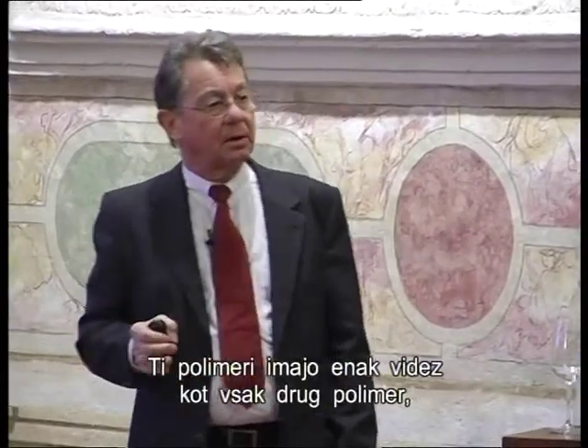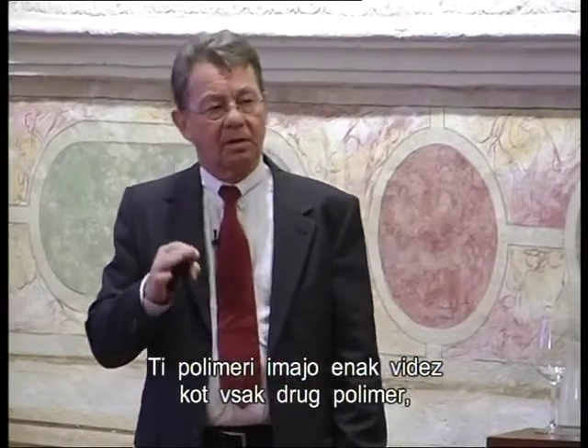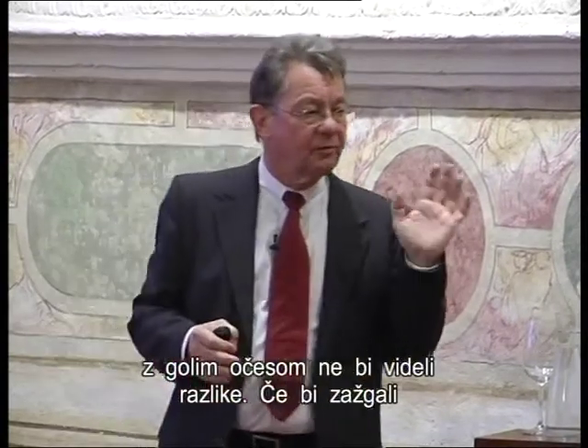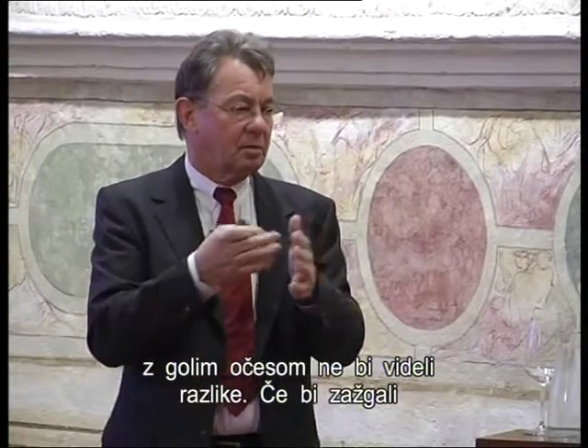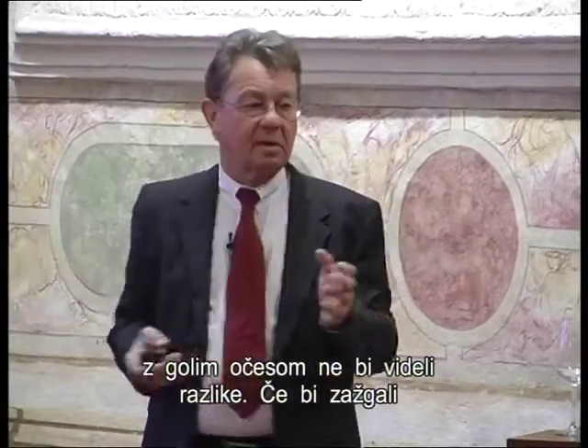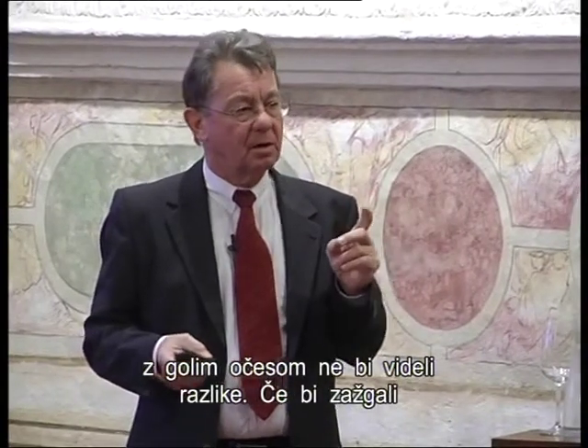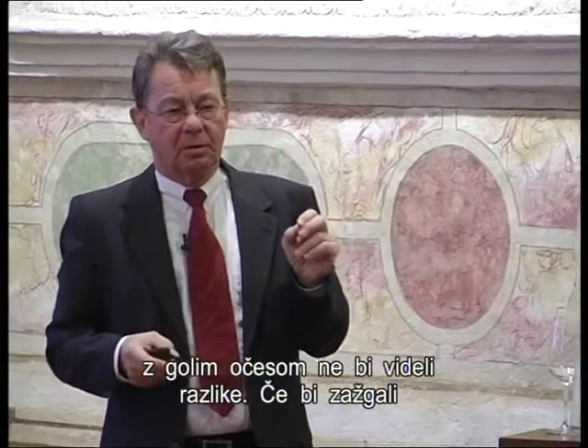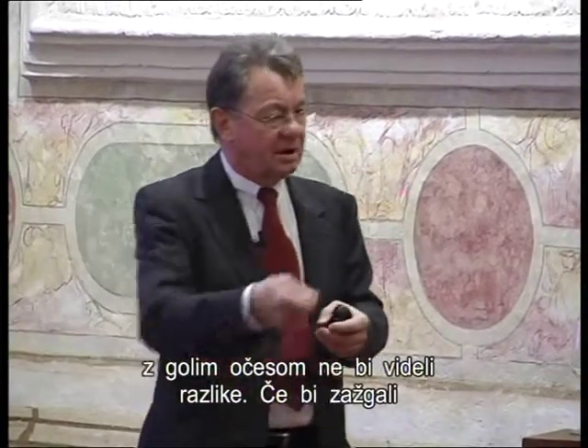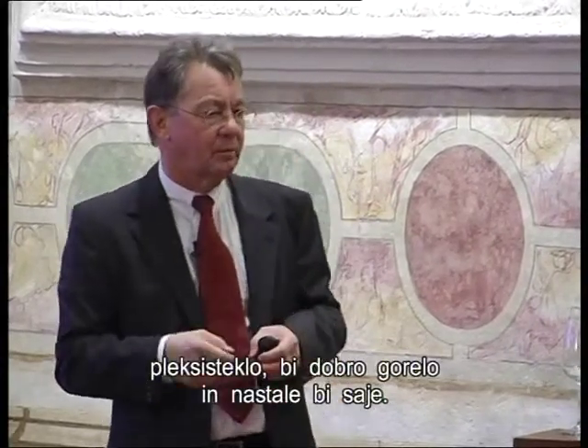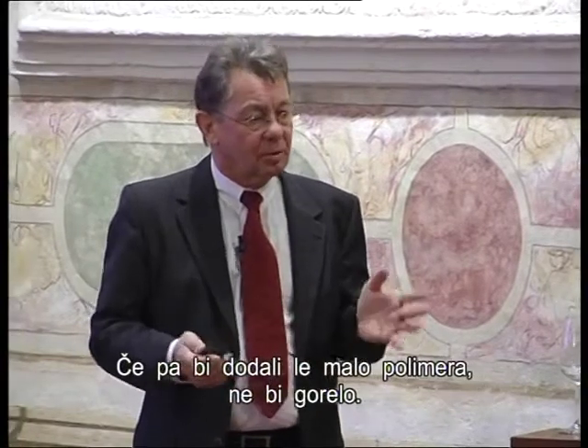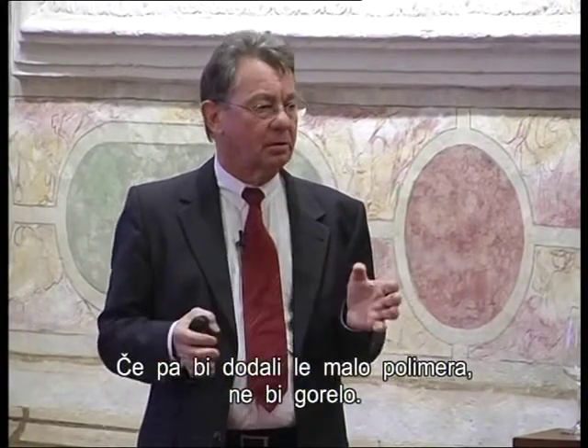The appearance of this polymer is the same as normal polymers. So if I would show you a piece of such a polymer, you wouldn't see a difference with the naked eye. Plexiglass, PMMA, doped with these clusters looks like plexiglass. But you would see a difference immediately if you take a match and ignite it. PMMA, plexiglass, burns very well and it develops soot. If you cross-link that with the cluster, it does not burn. So tiny amounts of cluster prevent burning. I can explain later, if you like, why it does not burn.